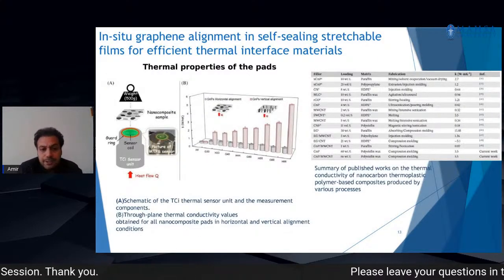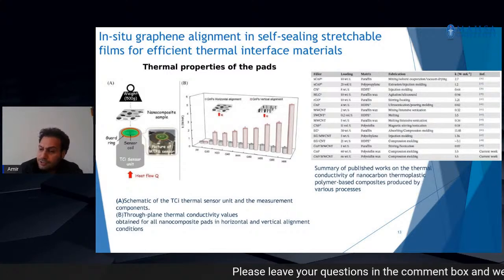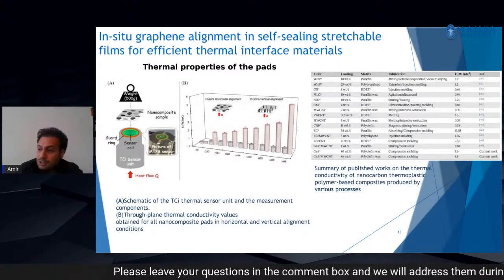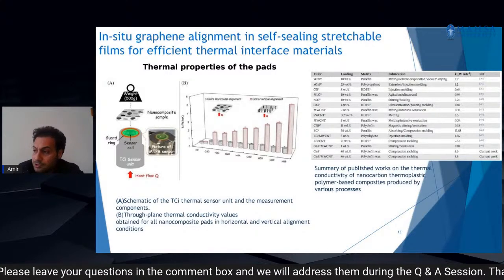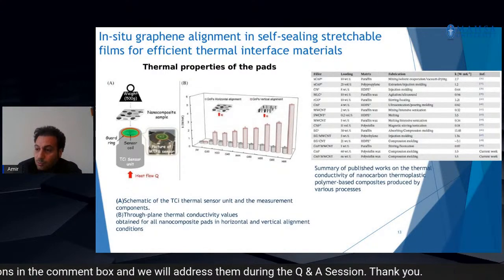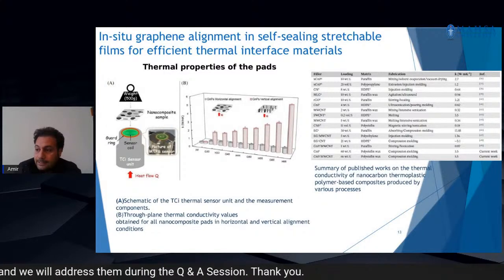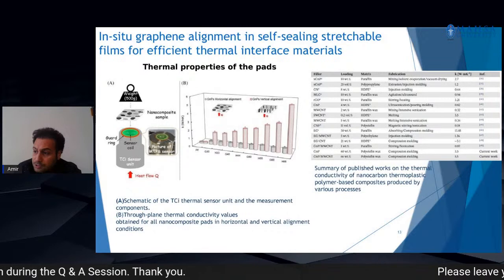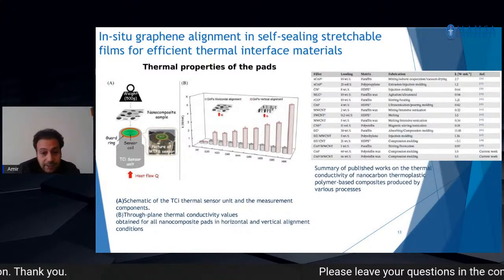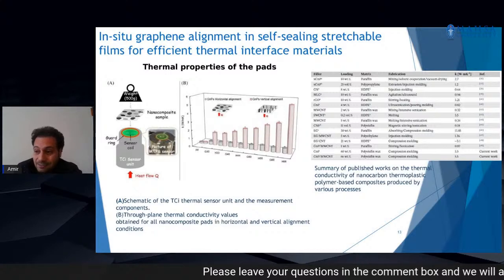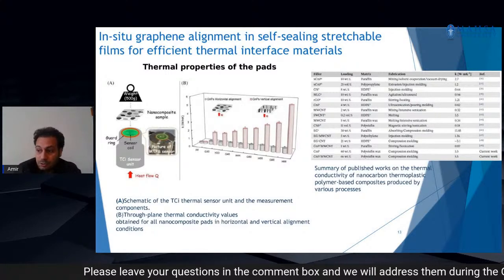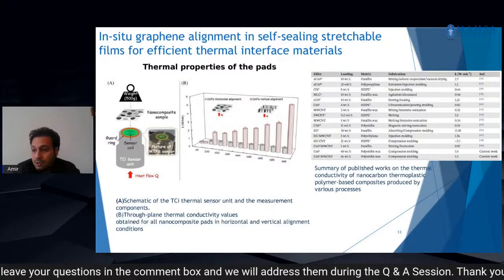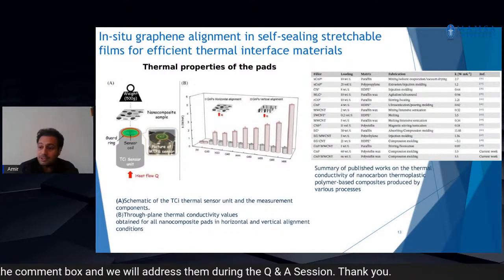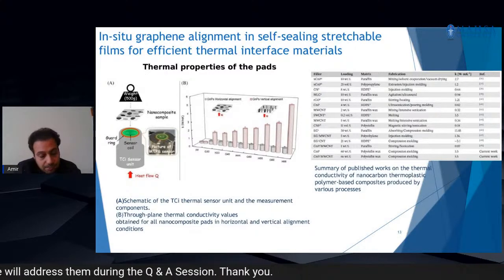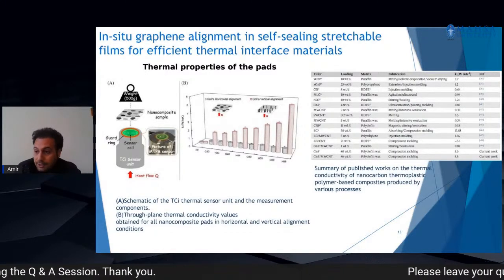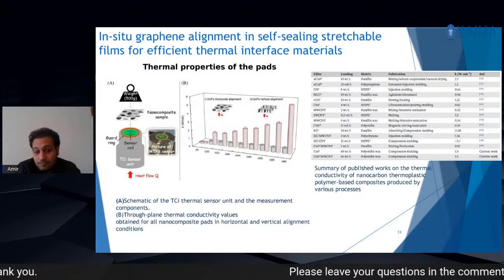This figure shows the schematic of the thermal conductivity measurement system for the nanocomposite pad that contained horizontally and vertically aligned GNPs. In the case of the nanocomposite with horizontally oriented GNPs, the applied heat flow direction is orthogonal to the orientation direction. And for vertical alignment, the heat flow is along the GNP's basal plane, in plane.